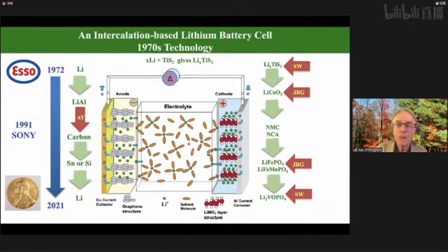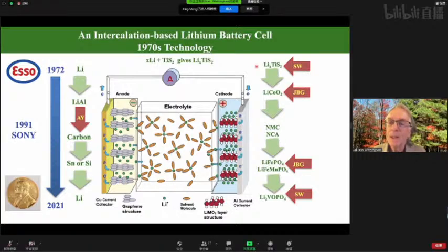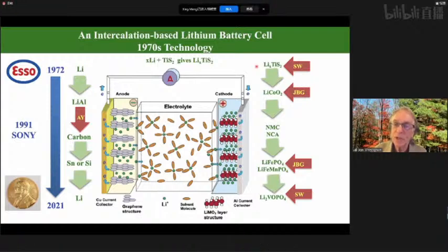If you look at the cathode, we started out with a layered compound, lithium titanium disulfide. John Goodenough, who was then at Oxford studying the magnetic behavior of lithium cobalt oxide, noticed a similarity in structures and studied this as a battery electrode, and all the rest is history. The challenge with cobalt oxide, though, the cobalt is rare and expensive, so most of the cobalt is now replaced by nickel and manganese or by nickel and aluminum.